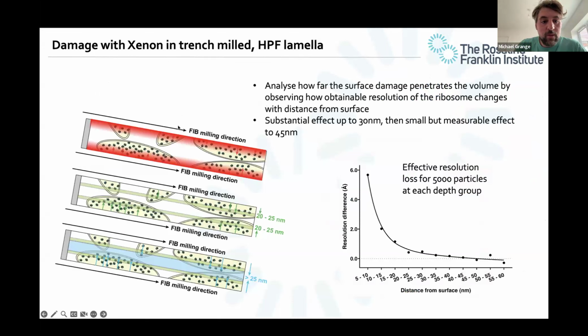But we then wanted to see how that compares to argon. And you can see here in this plot, essentially the distance at which the particles become essentially the same is around, again, 40 to 45 nanometers. So again, xenon and argon have a substantial amount of damage down to about 40 to 45 nanometers. And your best particles come in the middle, obviously beyond that point.